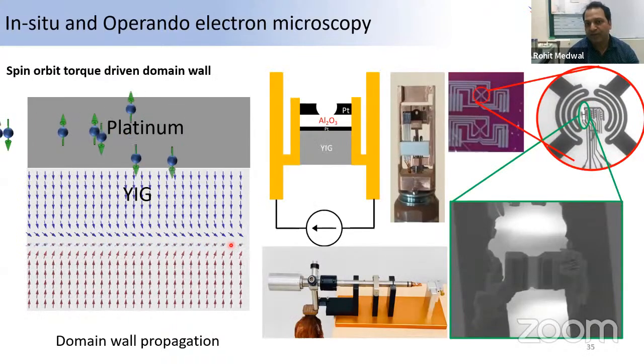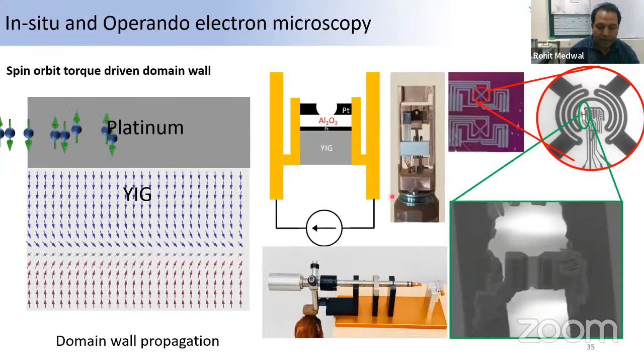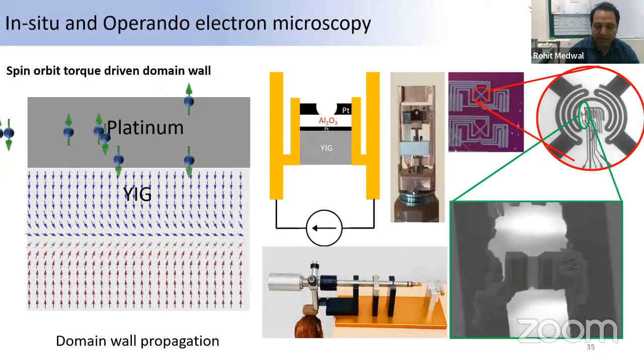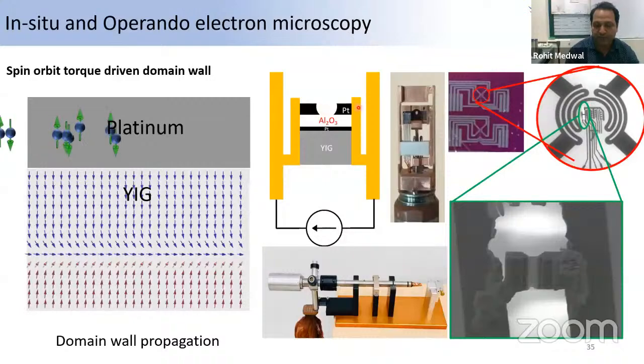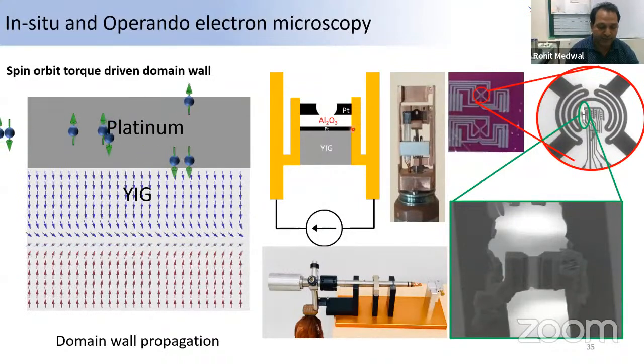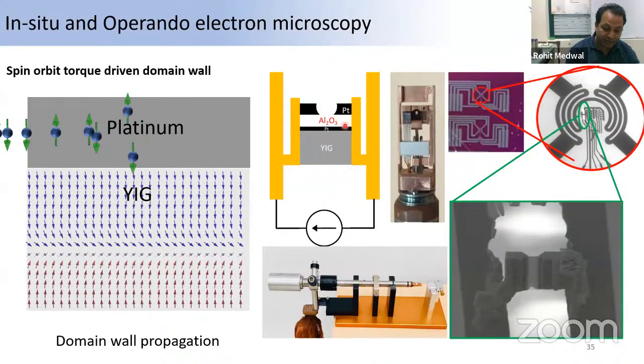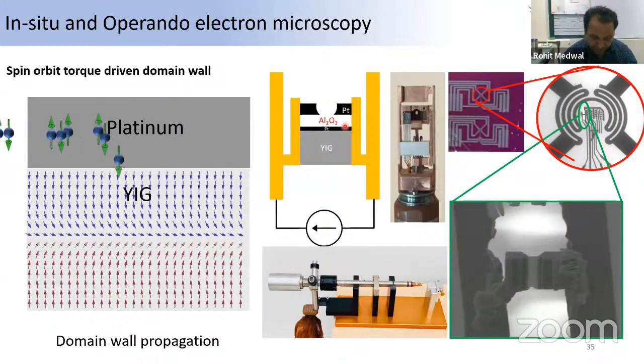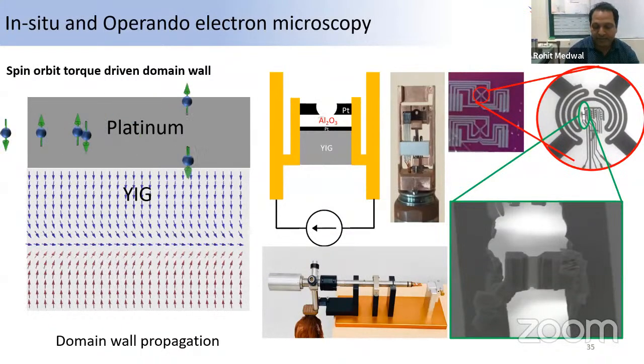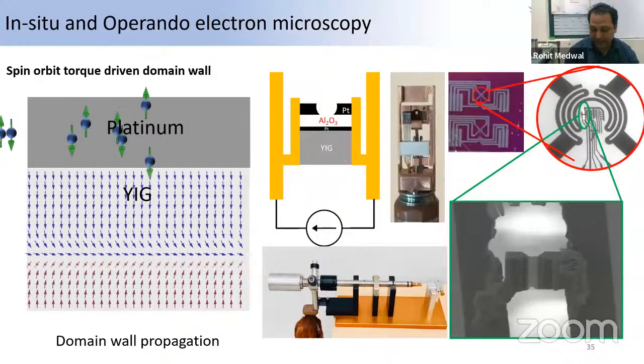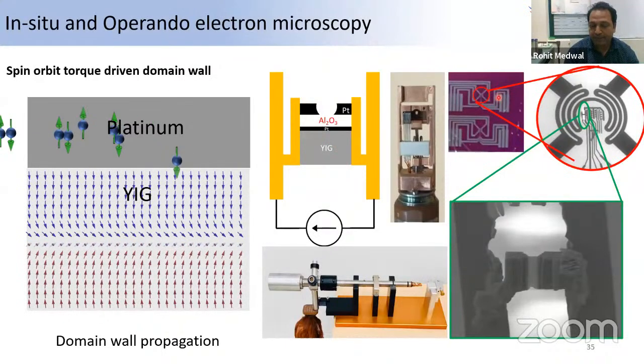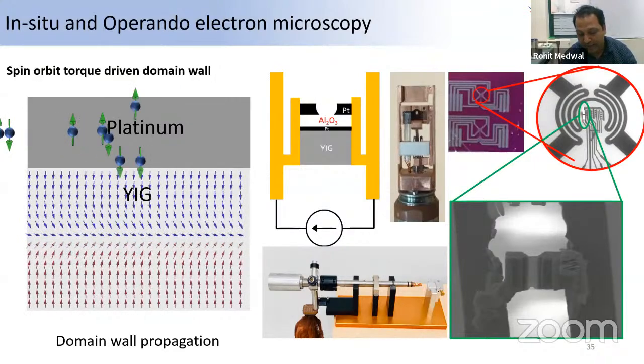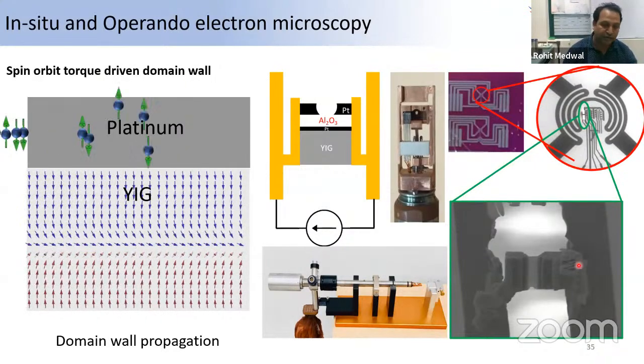For this, we designed this. This is a TEM holder. We designed this device. This is YIG interfacing with the platinum, Al2O3, and then a platinum cap. We cut it so that we cannot pass the current through the platinum. We can only pass the current through the thin layer of platinum, which is highly pure platinum. This entire device is the device structure, and this is our chip, the MEMS-based TEM chip, which we integrate with this holder, and this is our real device, which we image using the focused defocused wave.